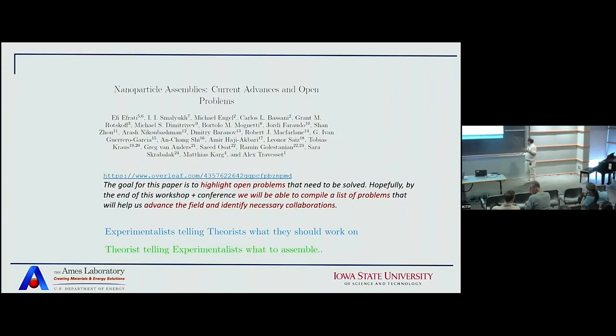But then when you have them in the lattice, that cannot happen because the entropy of these things is very low. So there are all sorts of new effects that take place. But the good news is that it's not as accurate, but the formulas that I showed still work. But again, I want to emphasize the formulas are for dry systems. When the system is swollen, then the polymer occupies a much more pervaded volume. And in that case, these formulas are not going to work. So once you are done with the drying, then is when the things work.